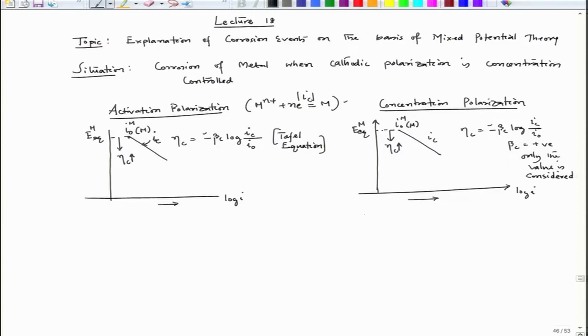Now, after that we have already observed that eta C, when it is concentration controlled, has the governing equation 0.059 divided by n log of 1 minus I C by I L. I could see that when I C reaches I L, eta C, which is the concentration over voltage, becomes infinite.